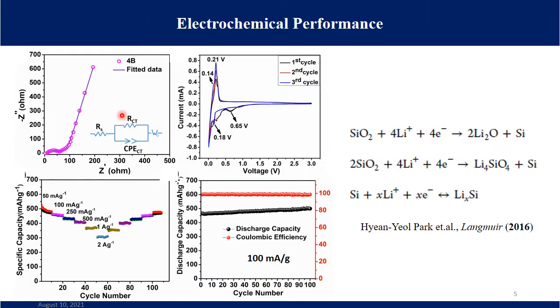We have performed various electrochemical characterization techniques for the 4B pencil lead powder anode. Initially, we have done the electrochemical impedance studies, and the EIS data was fitted with the equivalent circuit. The charge transfer resistance and the solution resistance are found to be 37.6 and 10.5 ohms respectively. The RCT value is significantly low due to the presence of electrically conductive graphite.